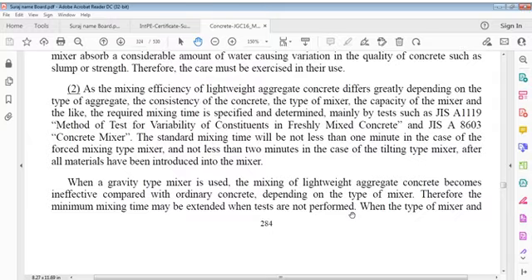Standard mixing time shall be not less than 1 minute in case of forced mixing type mixer and not less than 2 minutes in case of tilting type mixer after all materials have been introduced into mixer.